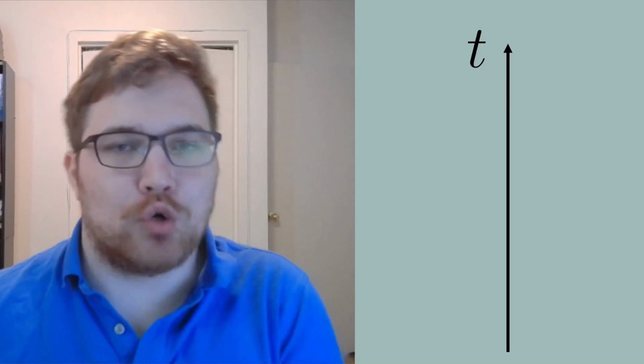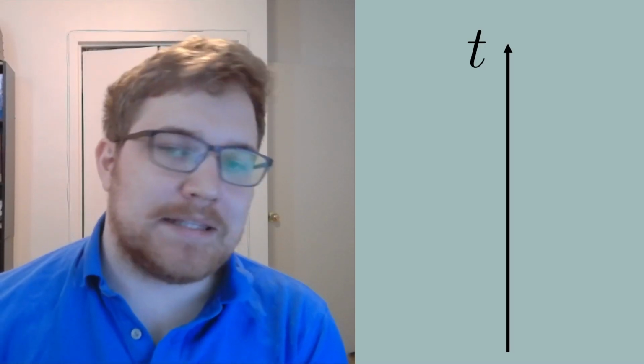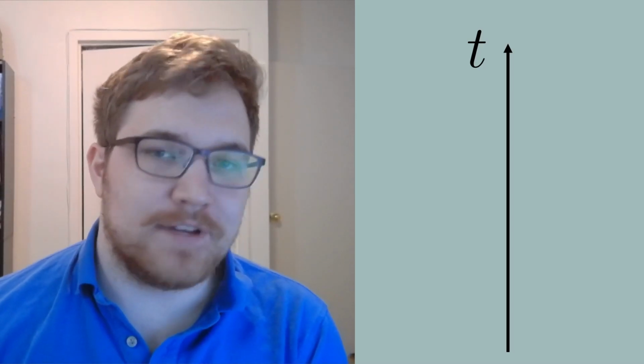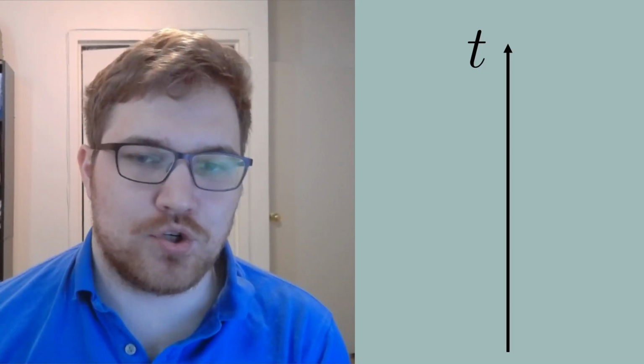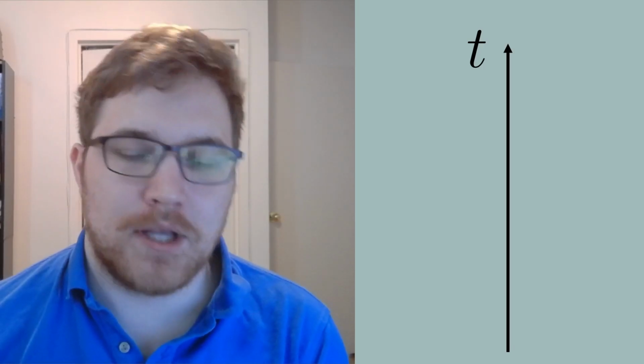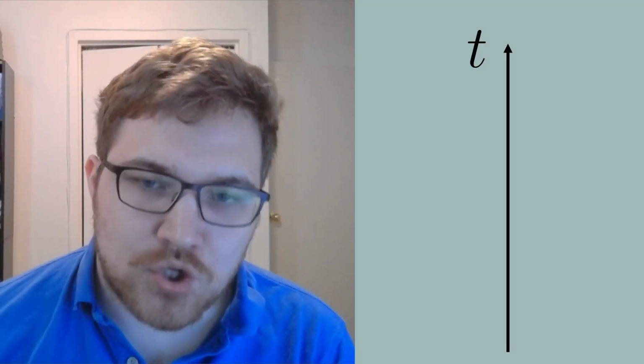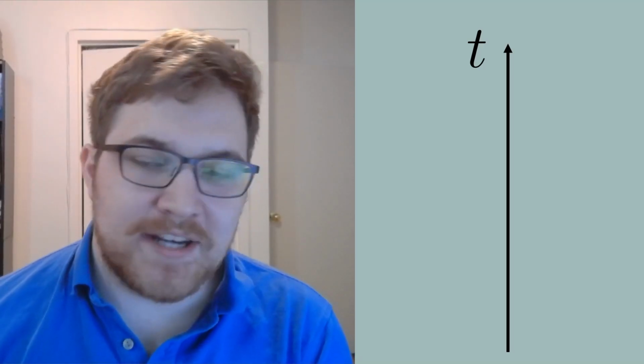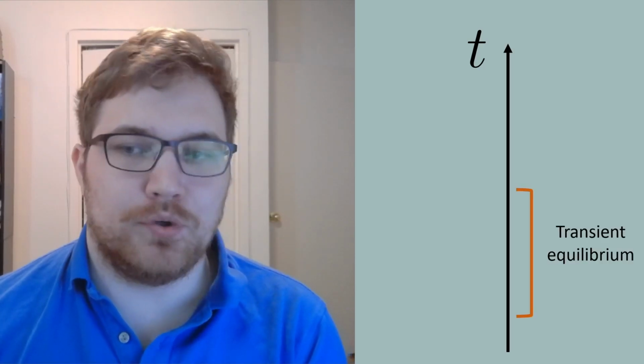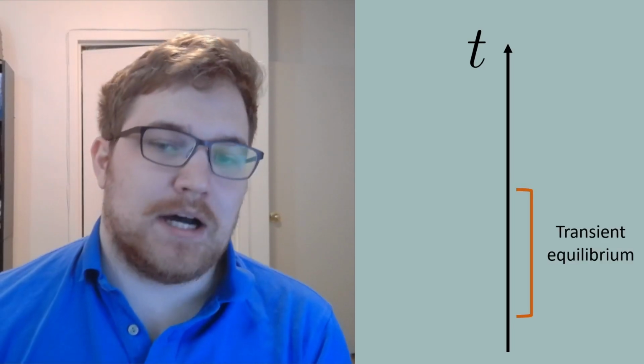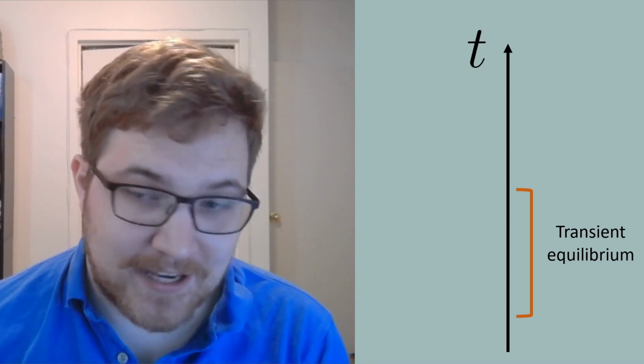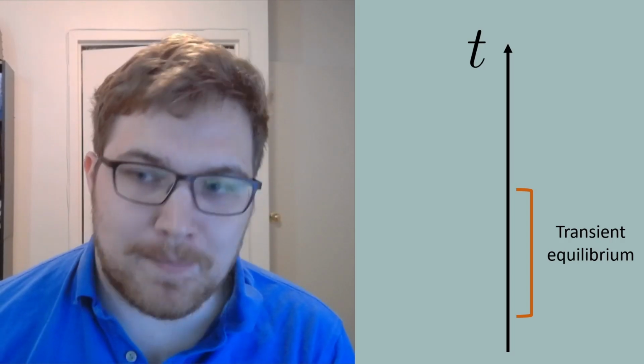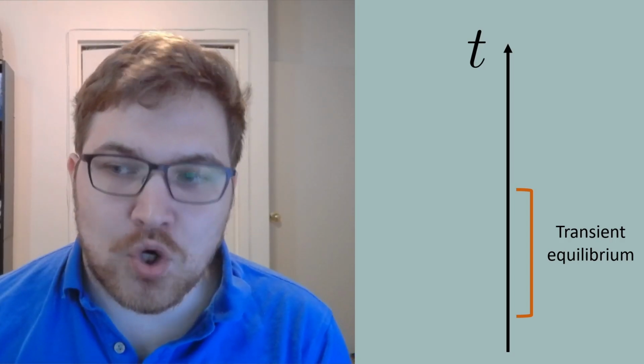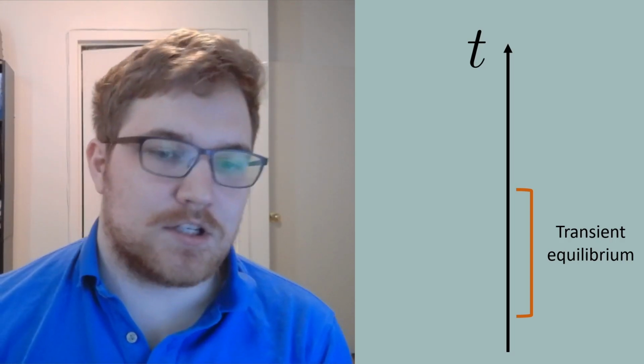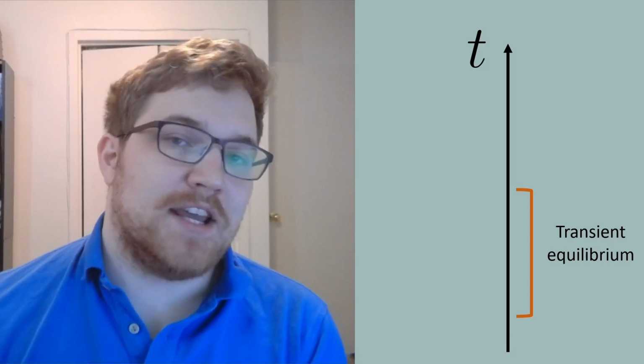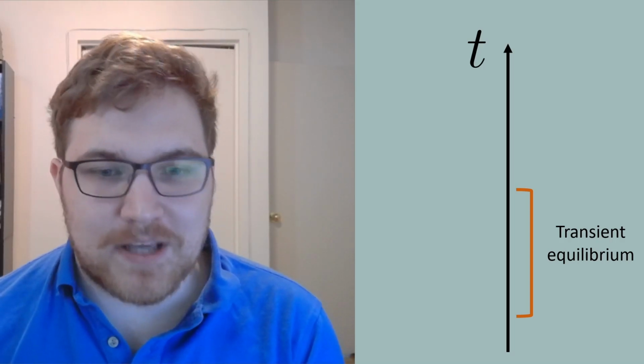These two timescales are radically different. As we said, the spin-lattice timescale is on the order of minutes or even hours, while the spin-only portion of the energy relaxes to equilibrium far sooner, less than a tenth of a second. Therefore, perturbation or disturbance from equilibrium will inevitably give us a transient equilibrium regime. In this short period of time, we are left with a system that can effectively only explore a finite amount of possible microstates, since only the spin degrees of freedom are being explored. This therefore allows us to potentially have a system with negative temperature.